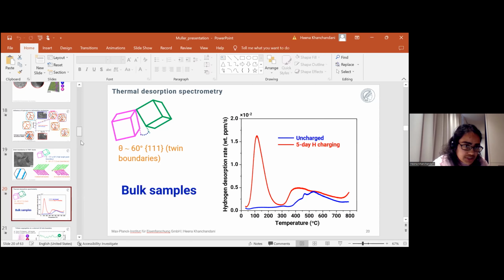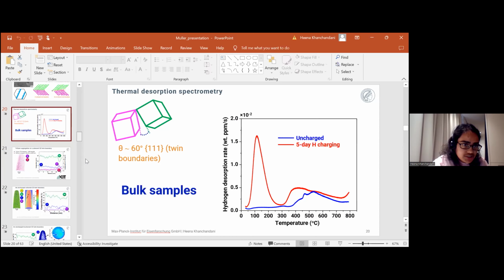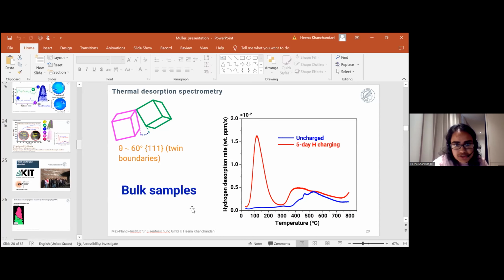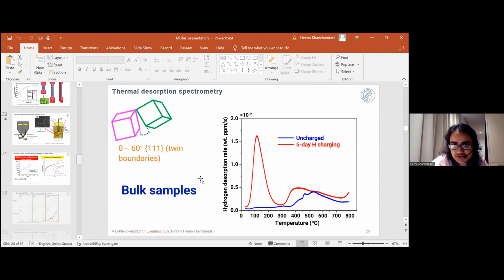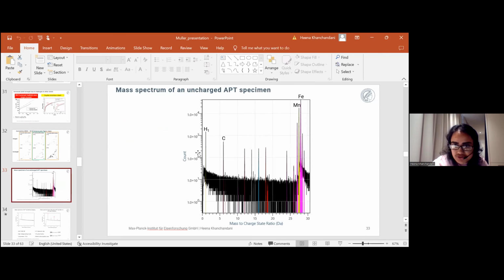Why could we confirm it? Because here is the mass spectrum of the uncharged material, where hydrogen is really detected only at 1. If I charge with deuterium, which is detected at 2, and deuterium was also detected at 4 in my data sets. And if I charge with tritium, which is detected at 3, then we can really confirm that it is tritium, because in the uncharged sample there is no peak at 3.